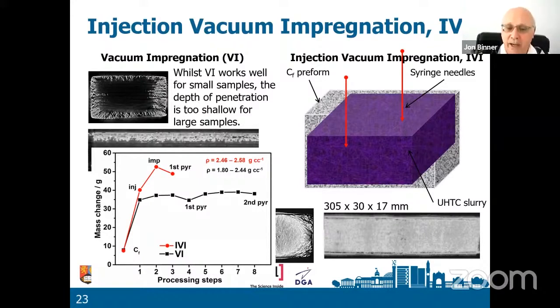The other big advantage is you use fewer processing steps. So with the old vacuum impregnation, you needed 8 different processing steps. And you can see the mass change there with each processing step. First PYR is first pyrolysis, and then second pyrolysis. The red shows the IVI approach. It takes just 3 processing steps: injection, impregnation, pyrolysis, and you've finished. You end up with something which is much denser. It's taken many fewer processing steps. So it's a much better route.